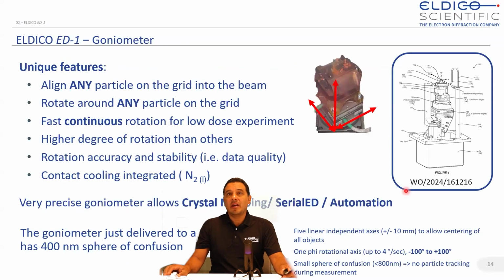Now let's go into the goniometer, the motors, which is very unique for electron diffraction. Because of the amount of motors, X, Y, Z, and rotator motor that we have, we can align basically any particle on the grid. We can rotate around any particle precisely. Moreover, we can do fast continuous rotation for low dose experiments. We have a higher degree of rotation than others.